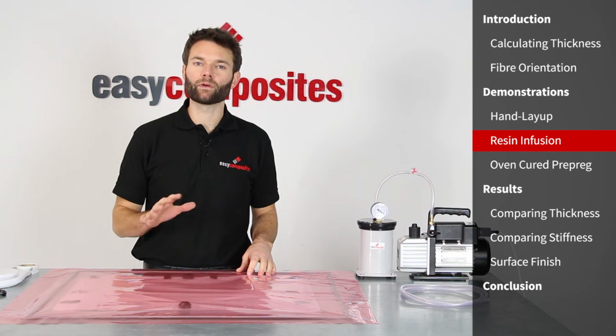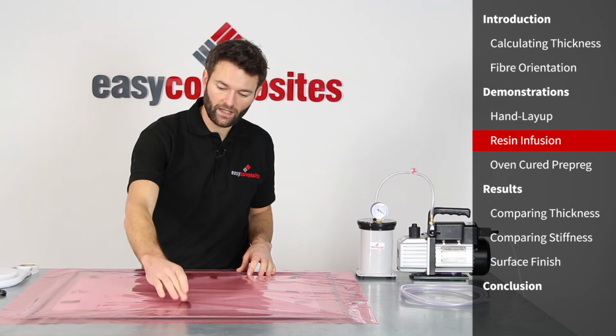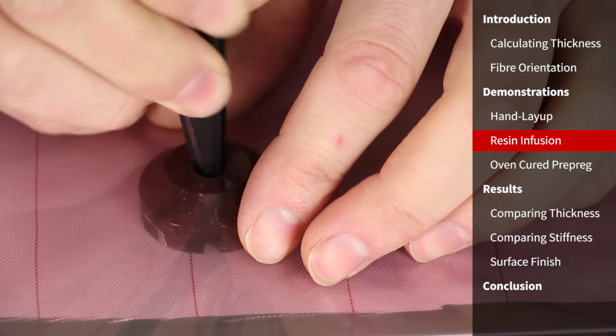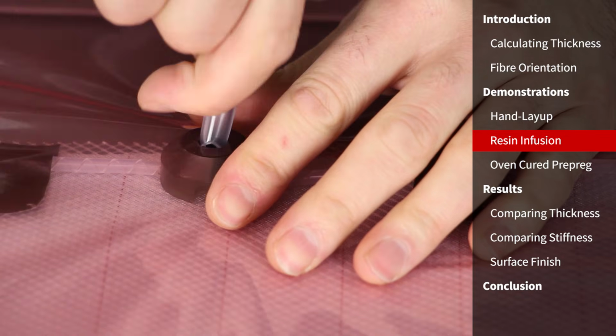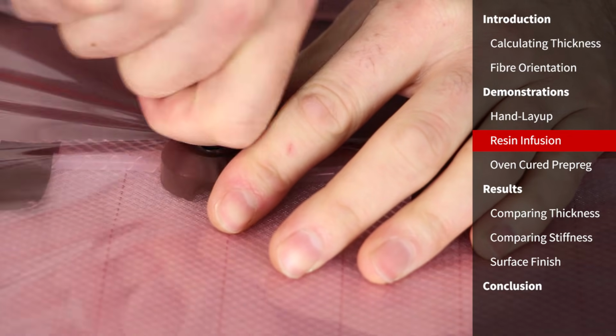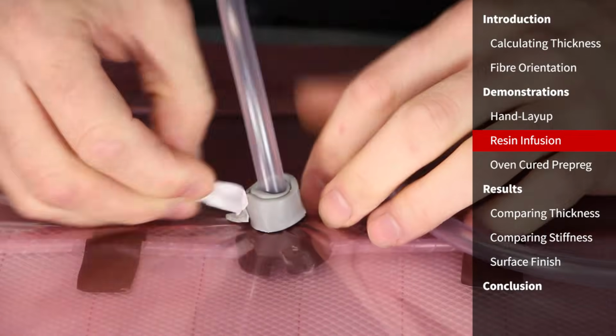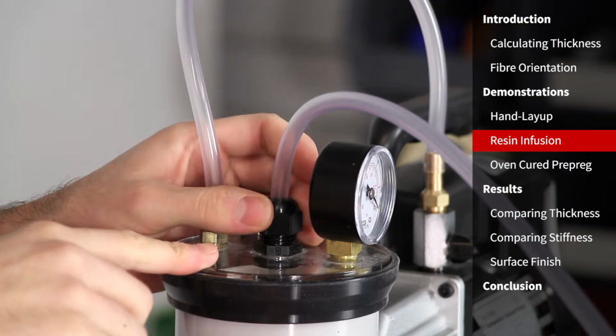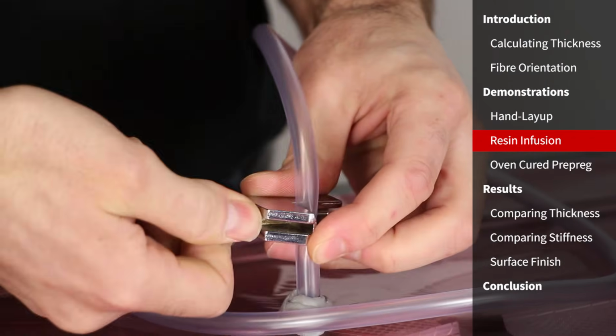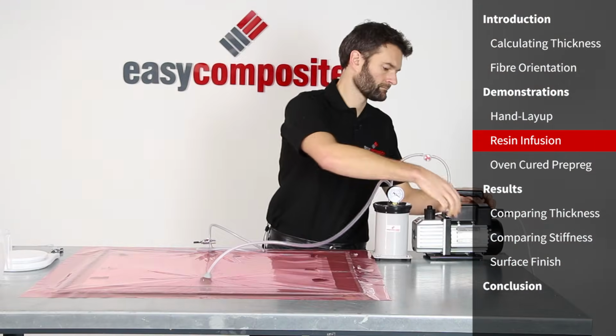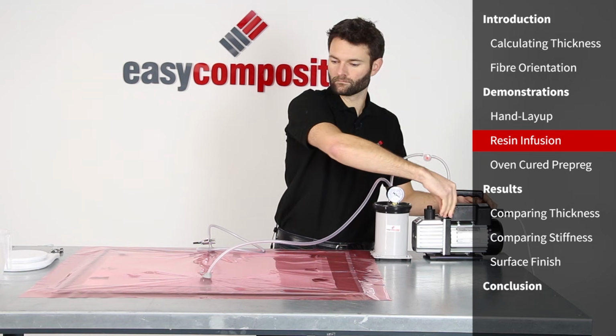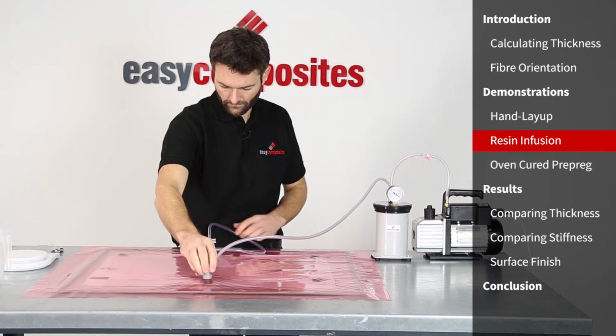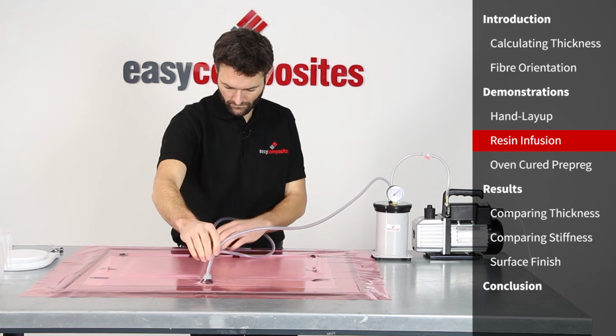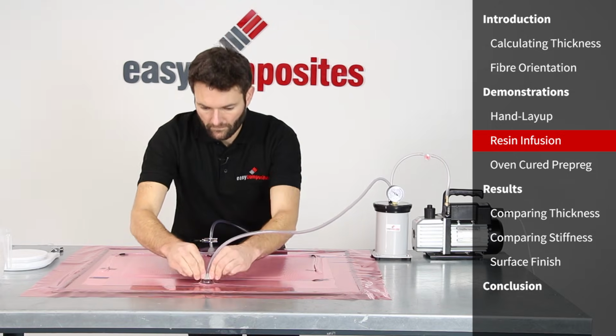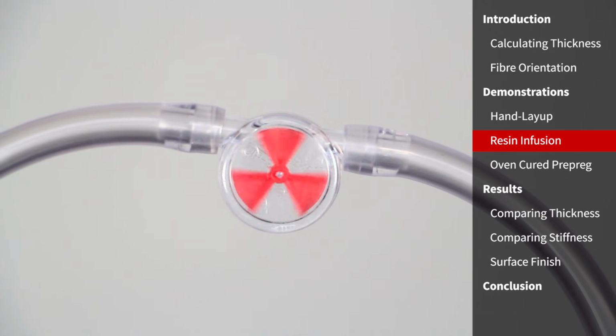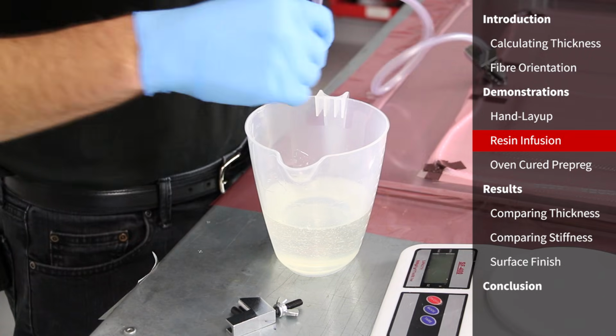The last stage of our very simple resin infusion setup is to just puncture the bag here and here for our resin feed and vacuum lines and connect them up to the vacuum pump and catch pot. You'll notice here the sloped cut that we've got on the PVC hose. That does help a lot in terms of getting that hose into the resin infusion connector. Now you'll notice with an infusion like a sheet, you've got very little air in the bag, so when we do switch the vacuum on, the bag will pull down very, very quickly and be at full vacuum within just a few seconds. What we've done is we've included a leak flow indicator in our circuit, and that's just quite helpful. We can keep an eye on that. It sits between the pump and the catch pot, and when that stops spinning, we know that we've got a pretty much perfect sealed bag.